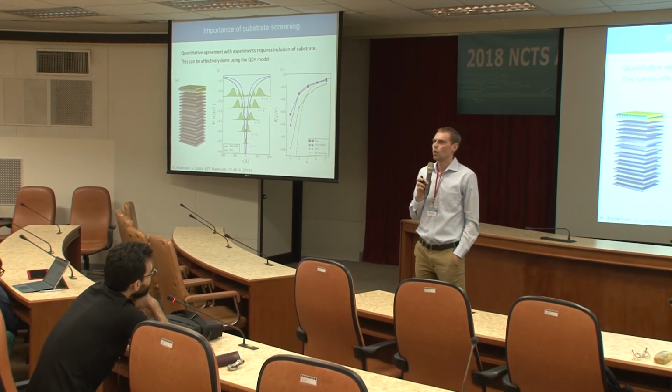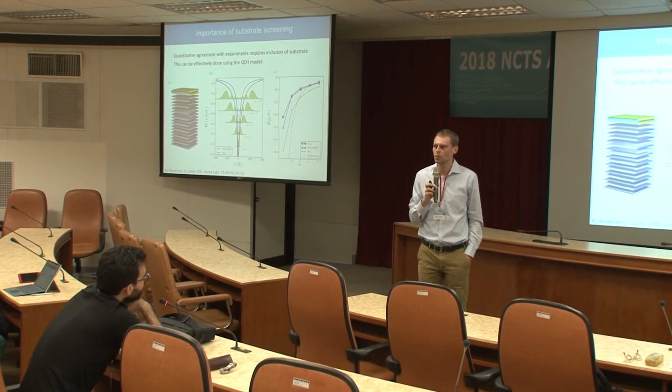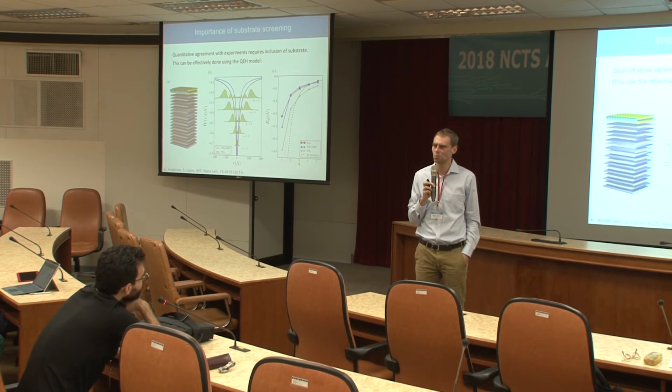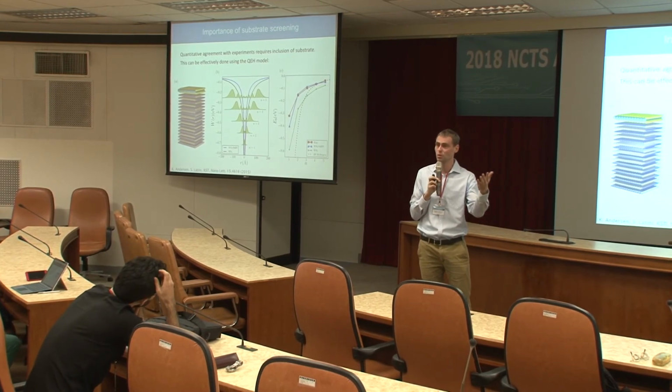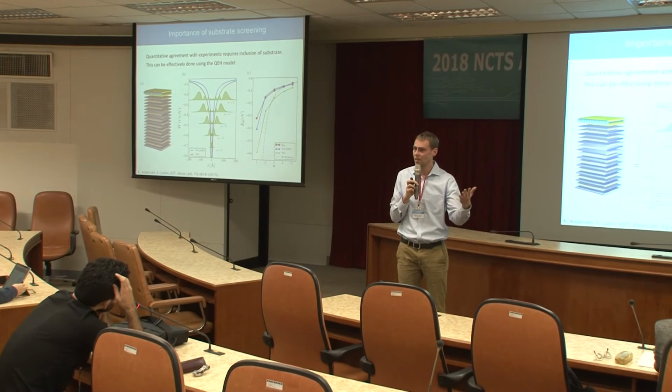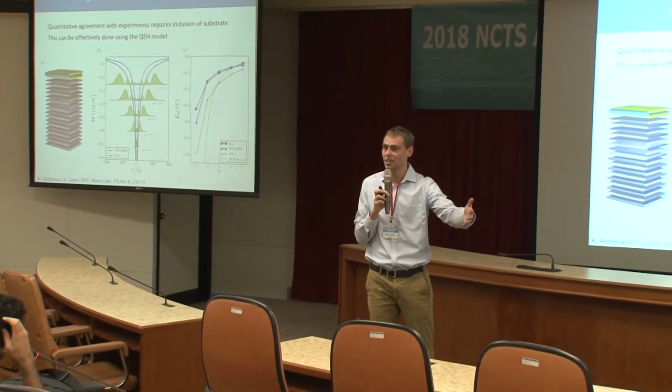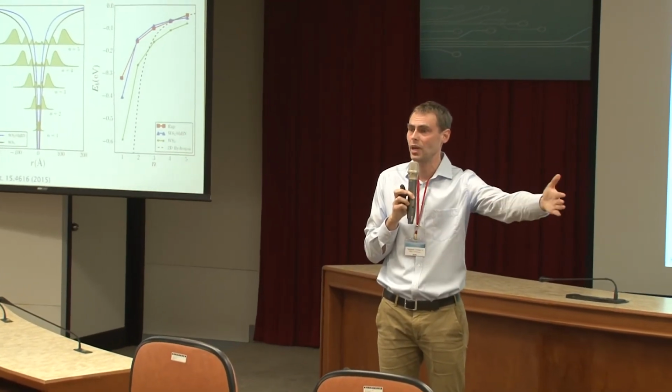Well, I guess if you have a large enough computer, you can just calculate the dielectric function. But I guess that's the problem, that you want to have a simple way of doing it. Because I think if you have a topological insulator, you have a metallic surface state. Yeah, exactly. And then you calculate the susceptibility chi. Of course, it will be a function of z and z prime, where z is the distance perpendicular to the layers. And obviously, when z and z prime are close to the surface, you will have a large dielectric response. But as you go towards the bulk, you will get a bulk-like dielectric response. So you have to find a way of dealing with this z prime dependence. But then I think one could do something. Yeah, but I didn't think about it explicitly.